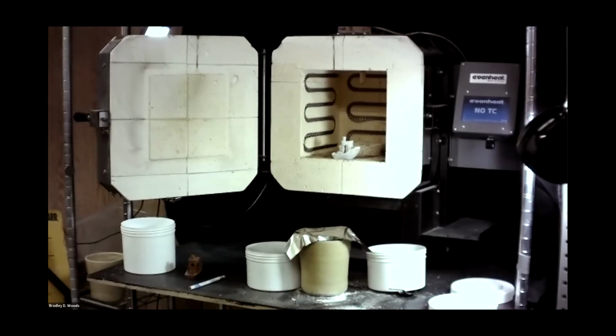Then once that goes into the kiln, you're running the debind and sintering cycle as one programmed time and temperature profile. So the steels are going to work as more of a single process. Copper and bronze are working as a sort of two-day or two separate step: debind, do some stuff to it, then sinter. And then you had said that the Pyrex is going to work more like the copper and bronze. You're going to do that two-day step with it, except the only difference being you don't need the sintering carbon.